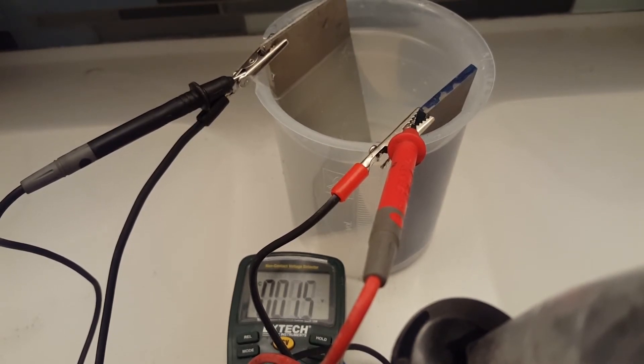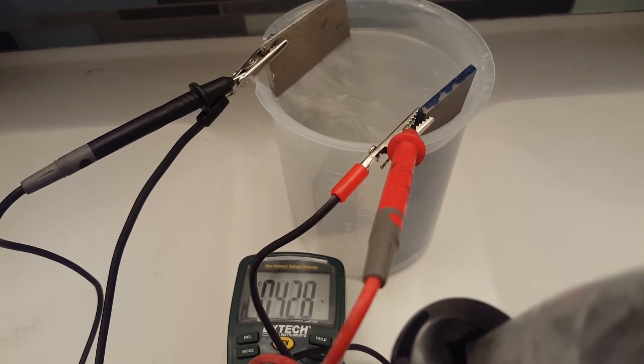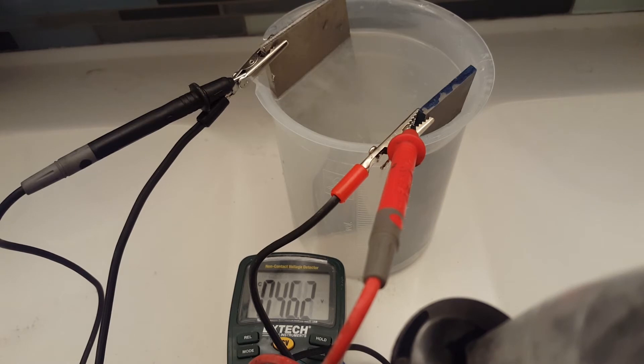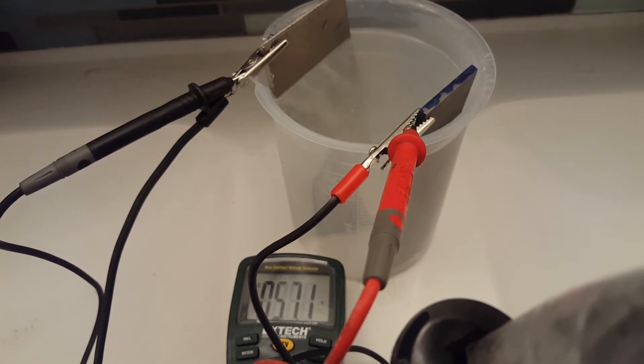We've got our power. We're going to raise it up to a higher level than the blue that we had before. The mask areas, hopefully, won't be affected. We're going for blue on yellow here. Yellow comes in the 50s. You can see a little bit of bubbling. Does look like a little bit of the mask has come free. 57. I'll turn the power off. We'll get our first look.